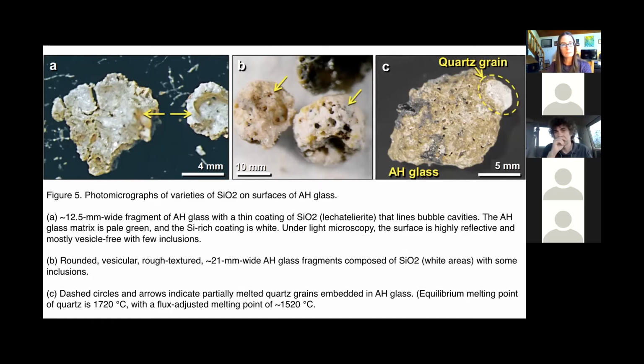In A and B. In C, you can see the glass, but there's a quartz grain. This is not the Lechatelierite, it's a quartz grain. But you can see there's a transition, where part of the quartz grain is molten and part is still present. So these things give you some idea, because the melting point of quartz is about 1720. However, when it's in contact with some other material, usually the temperature goes down, and it can be lower, like 1520. So we know it's between 1520 and 1720 when this melting occurred. I hear the ding. Thank you.